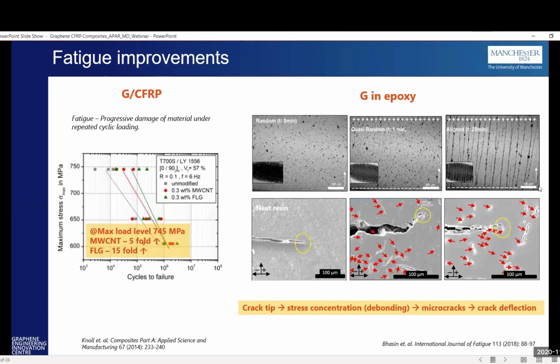And it's the same thing when it comes to the aligned graphene. The only difference is when the crack comes in contact with the graphene which is aligned vertically. The crack has to propagate even longer, or it has to go over the graphene nanoplatelets, which means it's absorbing more energy, thereby increasing the fatigue life.